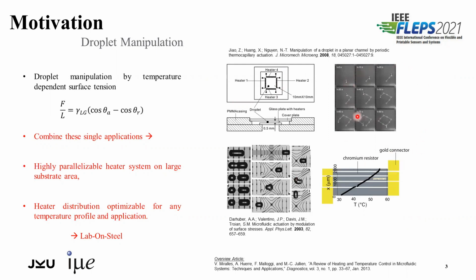There, for example, here, a droplet can be moved around due to different line forces at different positions on the droplet. And this formula on the left-hand side here shows the force per length which acts on the droplet's triple contact line, emerging from different contact angles on opposite sides of the droplet due to a local manipulation of the surface tension. For that, we need a temperature gradient along the droplet's interface,